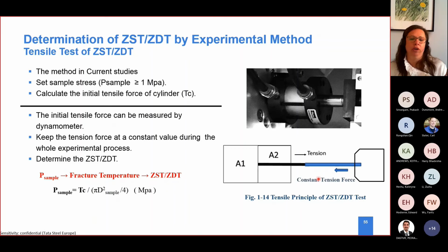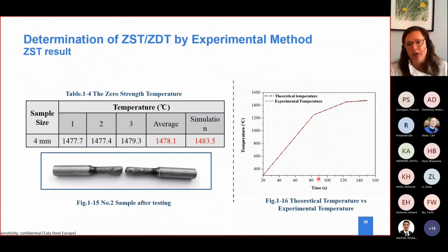You first pull it, and you keep that tension constant. For example, you say, I'm going to pull it at, let's say, 1 megapascal. So you first pull it, keep it in tension, and then you heat it up. At the temperature at which the sample with that exact fixed tension is going to break, that's the temperature associated with your hot ductility. So if you do that at different tensions, you can also follow the ductility trough. So you could have the zero strength and zero ductility temperature in an opposite way.